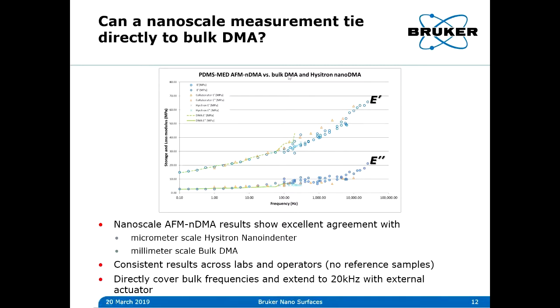And we also did extend the range, so you notice that the Hysitron and the DMA end at around a couple hundred hertz, but we're able to go up to about 20 kilohertz by using the external actuator. So back to Dalia.